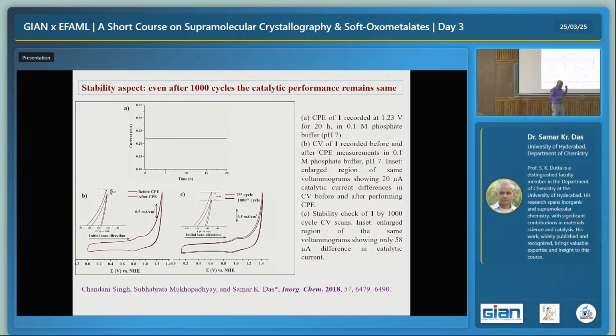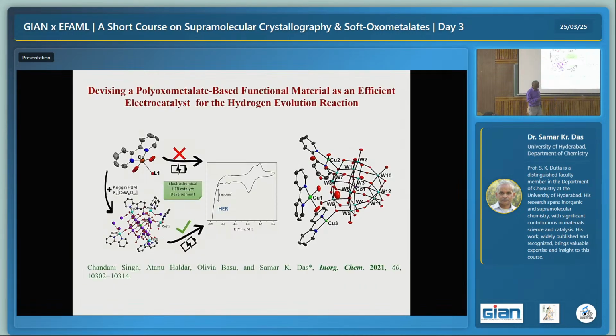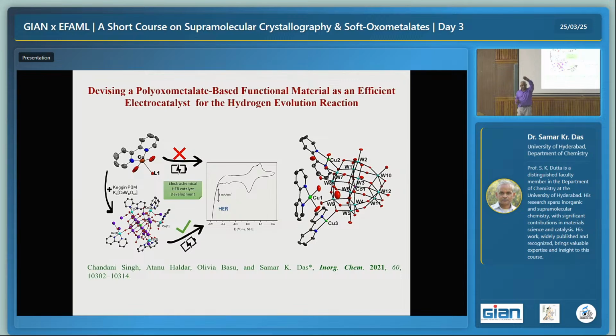So you can do like that. Very interestingly, the nickel compound gives water oxidation. Now, when we do copper, a similar bipyridyl copper, the same compound, we get hydrogen evolution. Why? This is the beauty of the metal ion, between the nickel and copper. In the nickel case, definitely when we get water oxidation, the metal has to go to a higher oxidation state, isn't it? Nickel goes to nickel(III), nickel(IV), coming back. Copper will get hydrogen evolution. We don't get oxygen gas. When we put it in the GC, we see hydrogen, of course happening in the cathodic window.